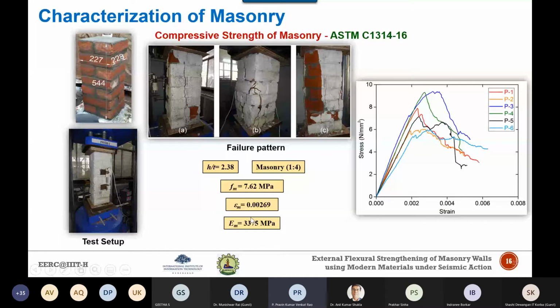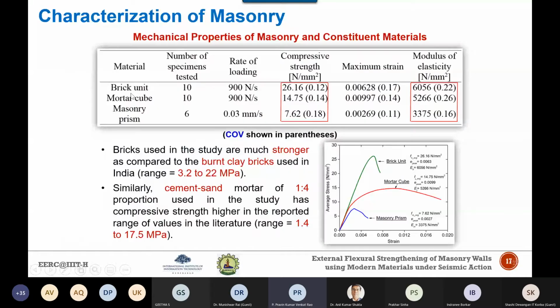Now let's see the summary. We have tested 10 bricks, strength of 26 MPa, mortar cubes 14 MPa, prism around 7 MPa. It is usually said that the masonry strength should come in between the brick and the mortar. But here you can see that the masonry prism strength is comparatively lesser than that of the brick unit and the mortar when it is a complete assemblage. The maximum strength of the masonry prism, which is 7, is less than that of brick and mortar, which is contrary to the generally believed stress strain curve of masonry lying between brick and mortar.